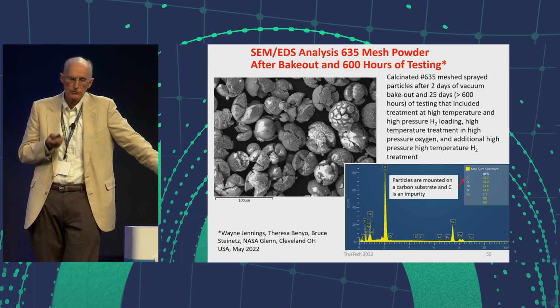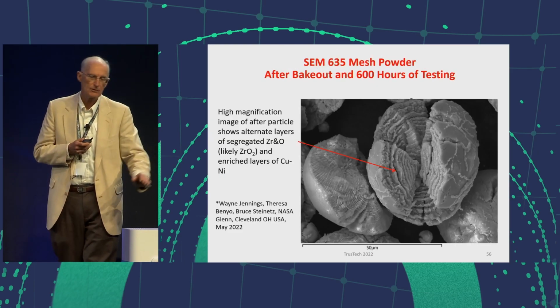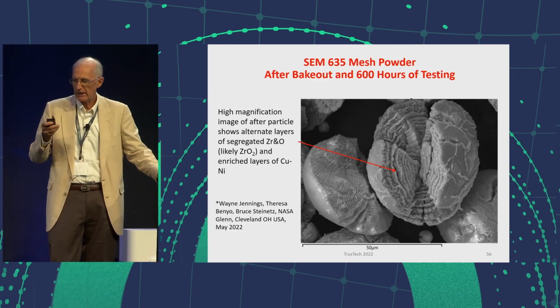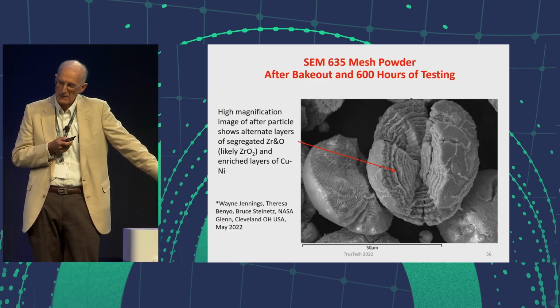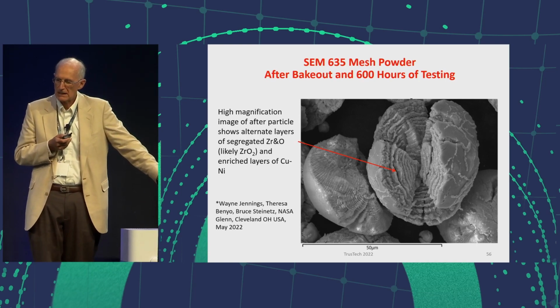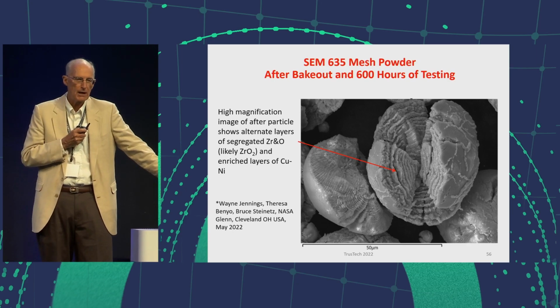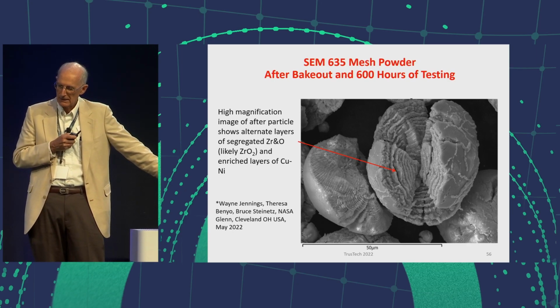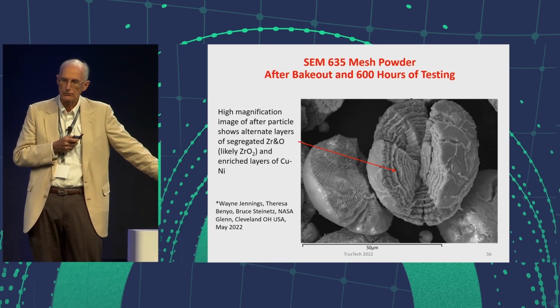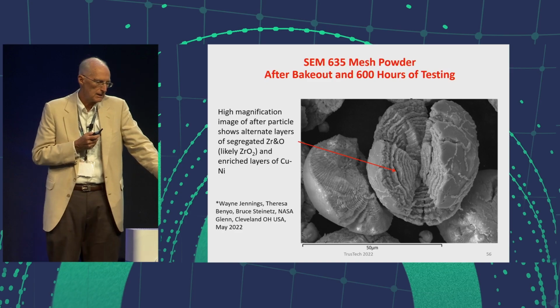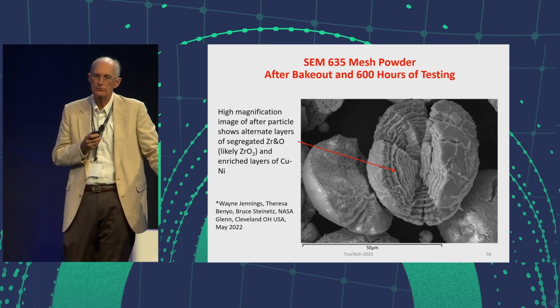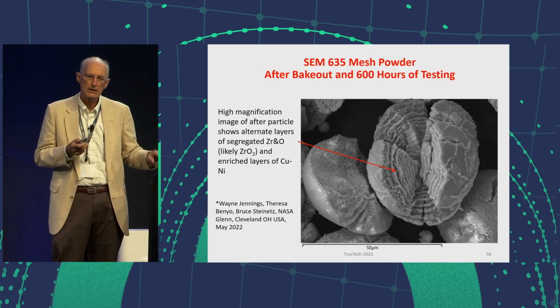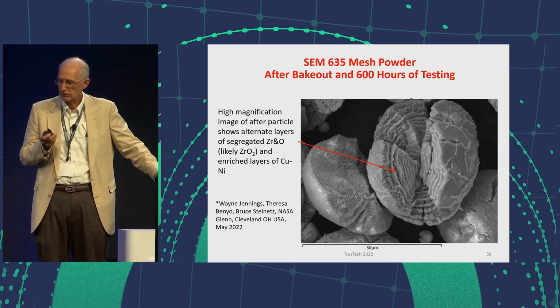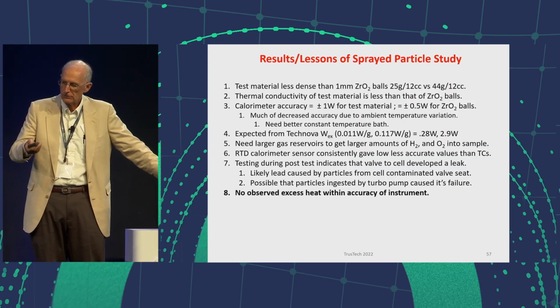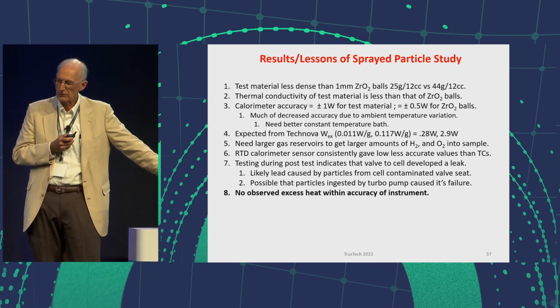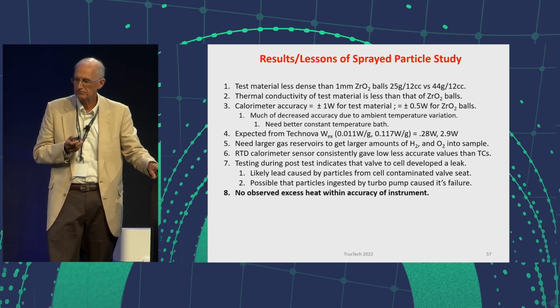But actually the interesting thing is if you take one of these particles and you blow it up and see it split apart, you see this layering on the inside. And according to Wayne, when you look at this layering, very interesting, each layer alternates between high zirconium and oxygen and high copper and nickel. So it seems to be separated in the layers, which is really surprising to me, but if it really is this situation, you wouldn't expect nanoparticles in a refractory of zirconium oxide, and this kind of process is not what you'd want to do. So these are results from it. The only thing I'll mention is the last one, that no excess heat was observed.